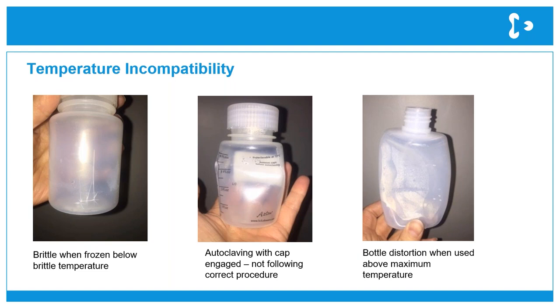The autoclaving of glass bottles was mentioned previously by Hanine, and a similar kind of process applies to plastic bottles. When you autoclave suitable plastic bottles, that is, bottles that can be taken to that temperature, the cap needs to be fully disengaged or ideally removed to prevent the buildup of pressure and implosion of the bottle. This is what you can see here. This was autoclaved with the cap on, and the pressure buildup has caused the bottle to implode. Even when you take the cap off, it doesn't return to its original shape. The last image on the right shows the result when a polymer is taken beyond its maximum temperature.